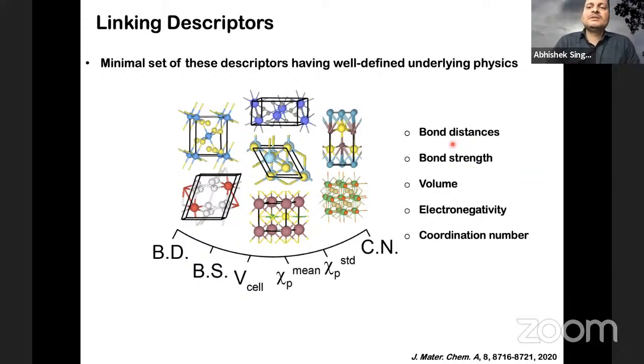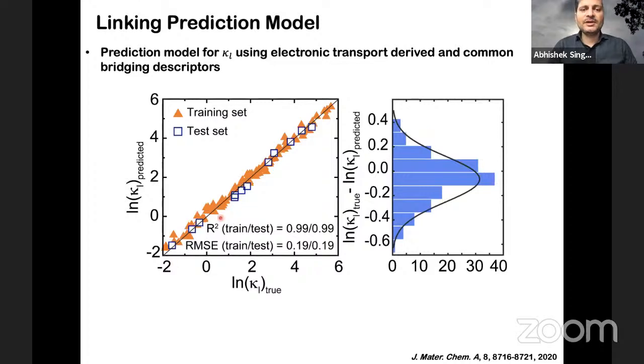So the one simple descriptor, bond distance, does have a correlation both with the electronic transport as well as the lattice part of thermal transport. And therefore, these are good bridging features, which come out automatically when you create these independent models. So we picked up these bridging features, added S and sigma in addition to that, and created a model for the kappa L. And look at how nice these models are. The R square is about 99%, and RMSE is as low as 0.19. And see that all the data falls within 2%. So the residual is also very low.